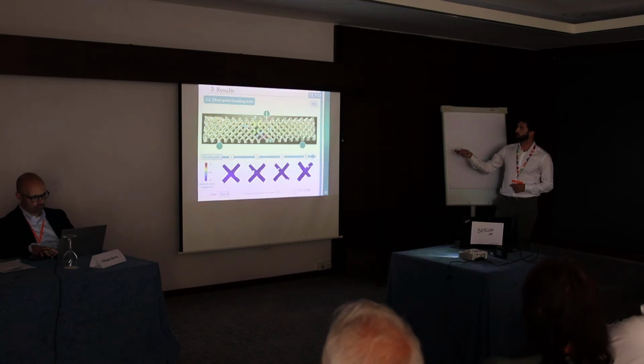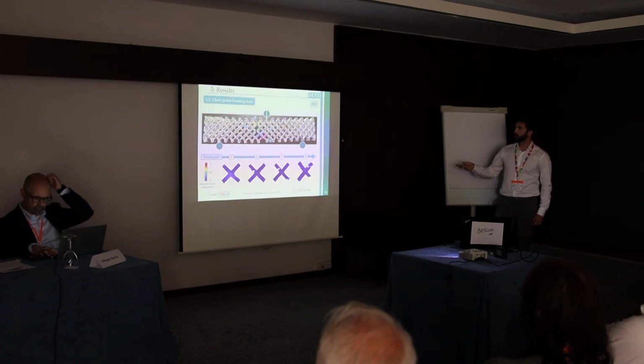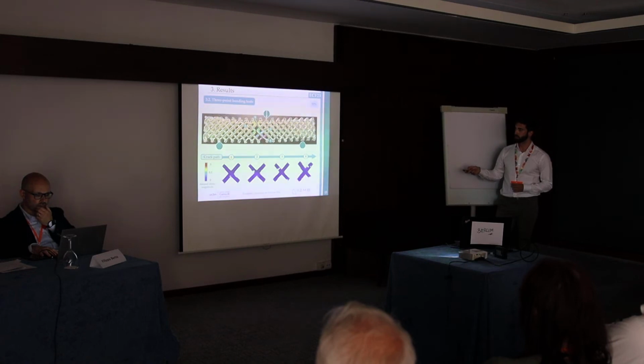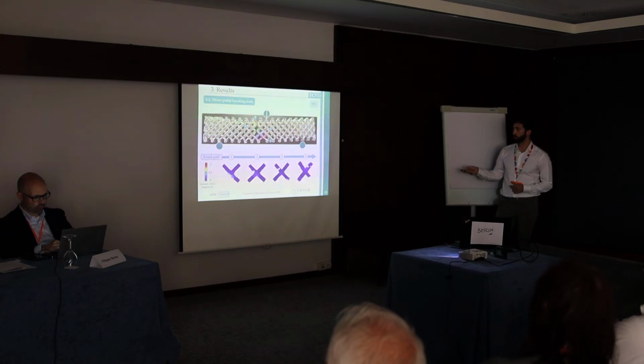Okay, so just for the 50% specimen, we have here the crack path of the specimen, with the two supports and the moving punch, and this crack path goes from 1 to 4. These are the joints of the infill, and here we have the result of the DIC, the digital image correlation, the strain in each joint. You can notice that in the first two joints, the strains are much bigger than in the other ones. In the other ones, the fracture is immediate.